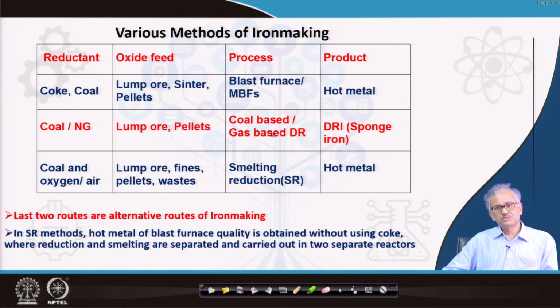In the coal based process, the name direct reduction derives from the fact that you are reducing the iron ore in the presence of carbon at high temperature, where carbon directly participates in the reaction. That is the definition of direct reduction, and that's why I call it the direct reduction process, because you can reduce the iron ore in the presence of coal directly at high temperature, at more than 1000 degrees centigrade.